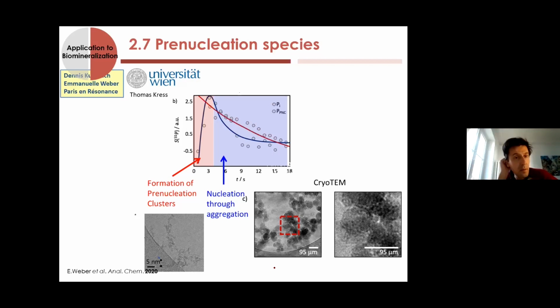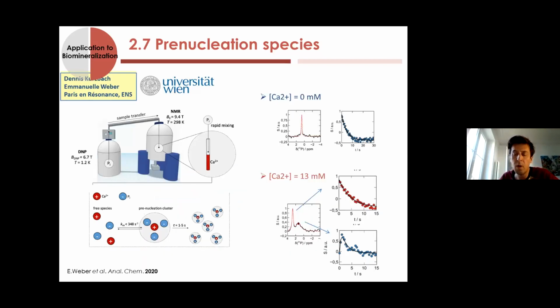Yeah, it's perfectly possible to have looked at homogeneous nucleation actually. Here we are using the DNP approach because the process is very fast, and we are tracking species that are not at a specifically very high concentration. If you see here, the concentration is 10 millimolar. It's not so much, and we try to decrease down to 1 millimolar because we want to be as close as possible to physiological concentrations. So that's why we are using it.